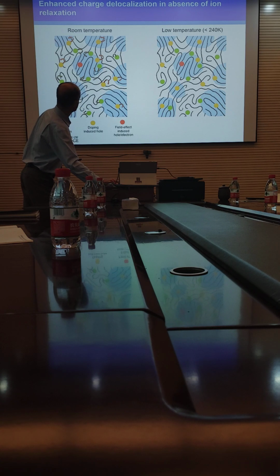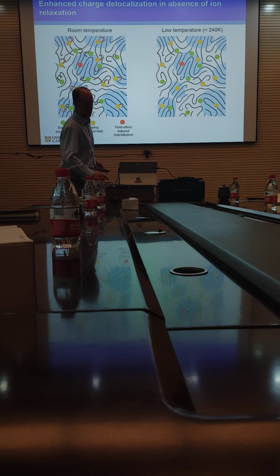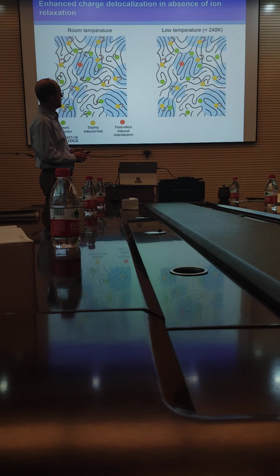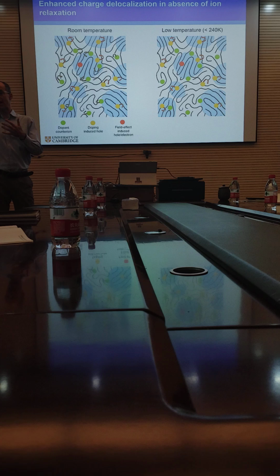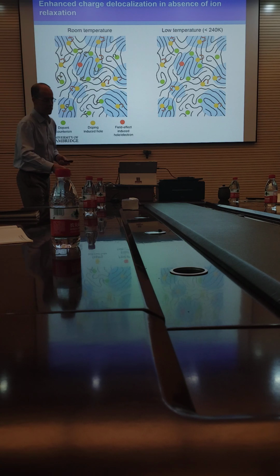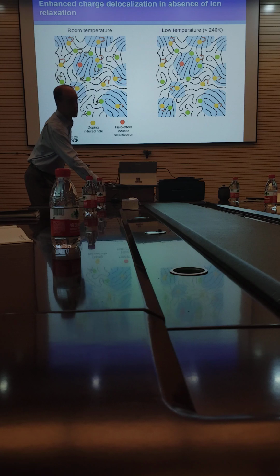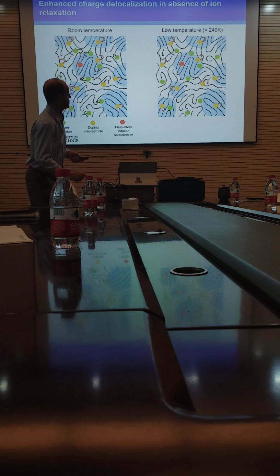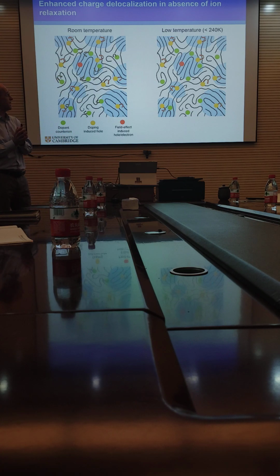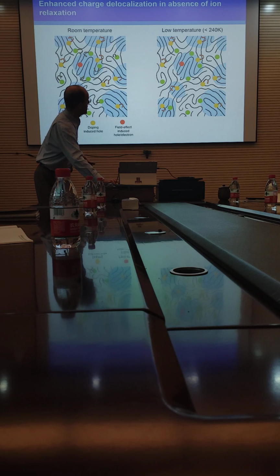This is the same experiment at low temperature. At low temperature, the electrons will still be able to move. They move away from that extra hole, but the counterions are not able to move. And so they stay in place. And we think that as a result of this, the extra charge,